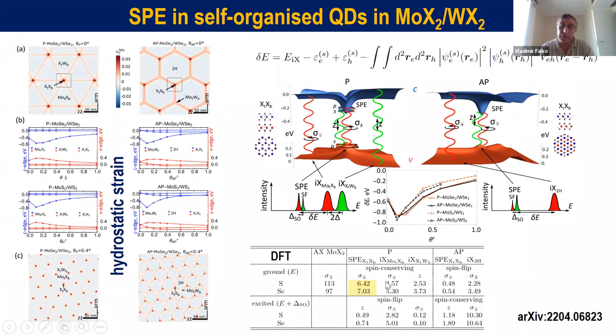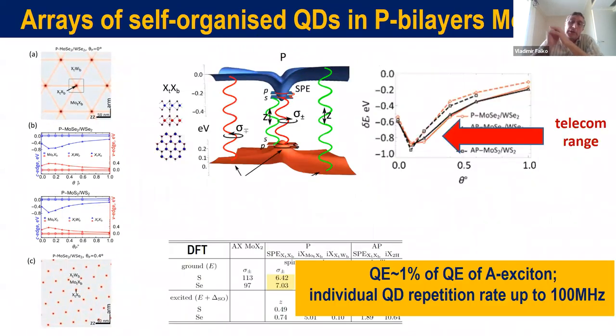Because of this, we calculated the optical polarization of these transitions. And for all possible polarizations, we computed the oscillator strengths, and we identified one transition in one configuration of the structures, which provides the strongest coupling between the exciton and light. And after we used the known parameters for the quantum efficiency of the exciton and the computed values for the optical oscillator strengths of the exciton, we came to the conclusion that we get a quantum efficiency for this quantum dot emission which may be 1% of the exciton in molybdenum diselenide or molybdenum disulfide.